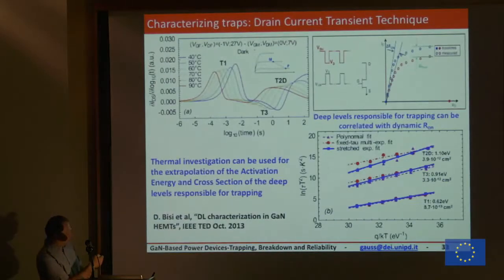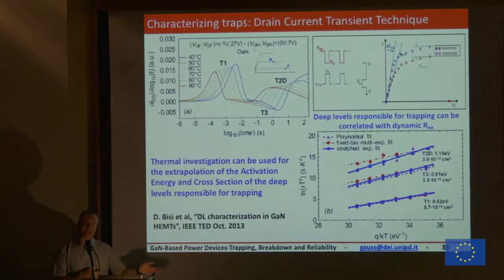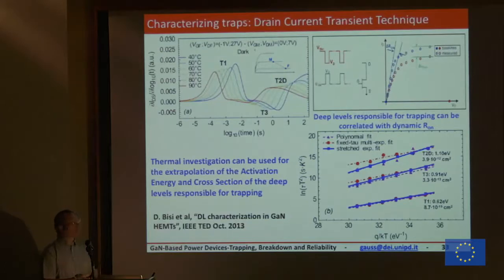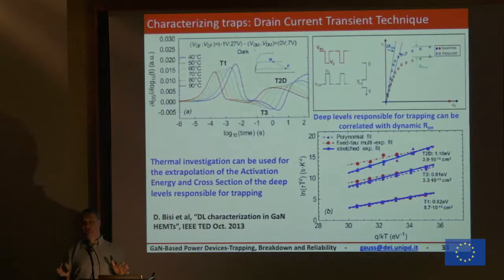But it is much easier for me to follow this point, and then from this, this peak moving as a function of temperature, as well as this peak and this peak, I may plot what we call the Arrhenius plot. I have no time to go into detail for this. I suppose you know about the Arrhenius plot. But plotting the log of the time constant, the peak of this, versus Q over KT, which is just the temperature, I see these lines, and from the slope of these lines, I can understand the activation energy, 1.1, 0.91, 0.62, and we can also extrapolate what we call the cross-section at infinite temperature. Again, now we started to have important information.